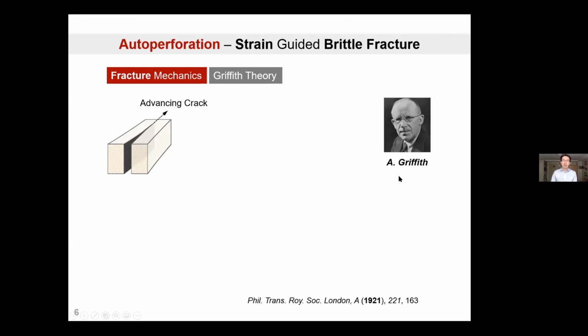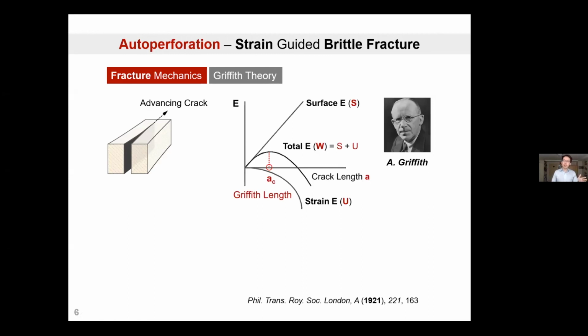It turns out this problem was solved almost exactly 100 years ago by Alan Griffith. He's the founding father of modern fracture mechanics, and he put forth the Griffith Theory to describe the fracturation process of any given material. According to his theory, when you have a piece of material and you advance a crack within the material, that is going to expose new surface area. If you plot the overall system energy as a function of the crack length, you see that the surface energy scales linearly with the surface area that you expose, and hence it's linearly correlated with the crack length.